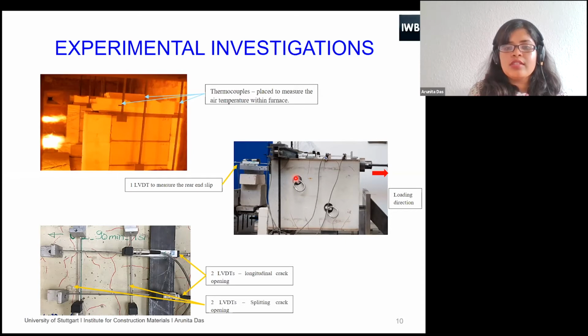Later on, in order to calculate the slip of the rebar, the elongation of the rebar is deducted, and we calculated the slip. On the top of the specimen, we have installed 4 LVDTs to measure the crack opening. Here you can see a closer view of that. There are 2 LVDTs which are placed to check the splitting crack opening, and these are the 2 LVDTs to check the longitudinal crack opening. We have placed 2, so later on we have averaged the values of these 2 and considered that as the final value of the crack width.